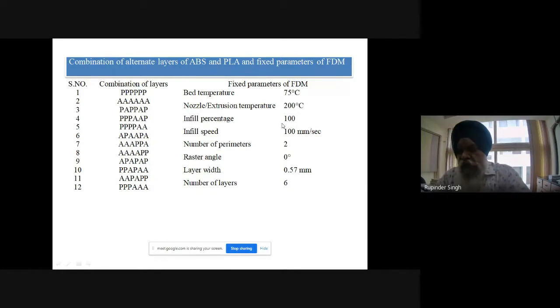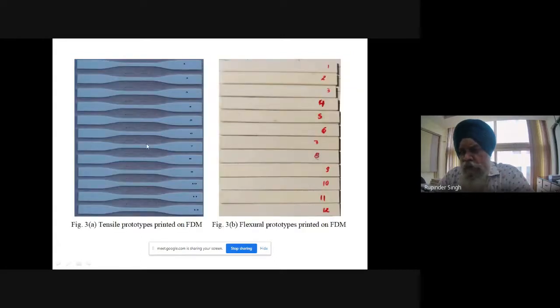So what we did actually, since I have to put 6 layers, we used the concept of random numbers. Initially all the layers were of a single material like P, P, P, P, P, P. So all 6 layers were of PLA. Then in another experiment, all the 6 layers were of ABS, right? Then at random we selected a first layer of PLA followed by a layer of ABS, then PLA, then PLA, then ABS, then PLA. Similarly, at random, without following any design of experiment, we observe the effect of different layer combinations, right? So these are some of the samples that were printed.